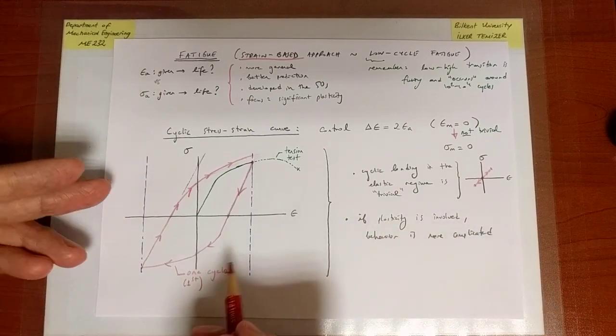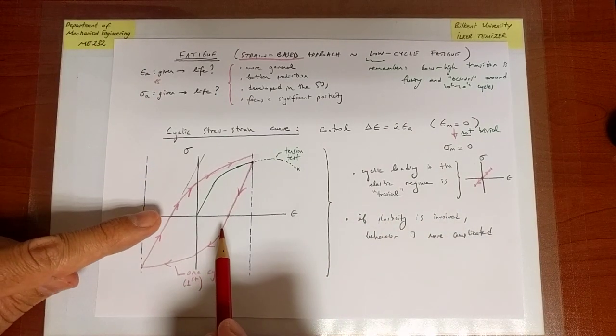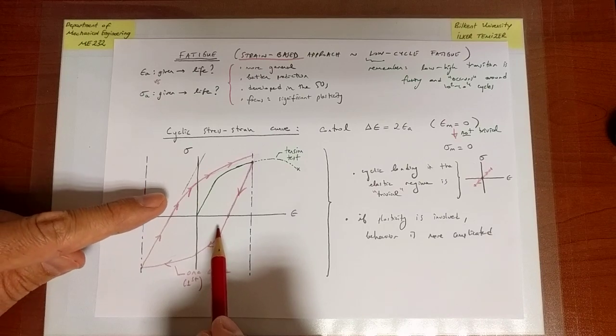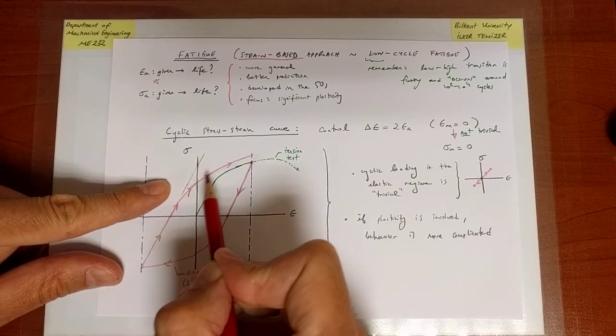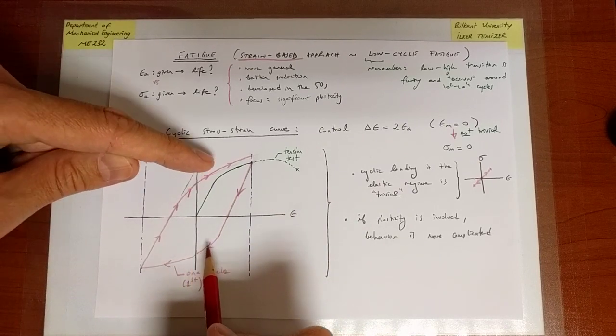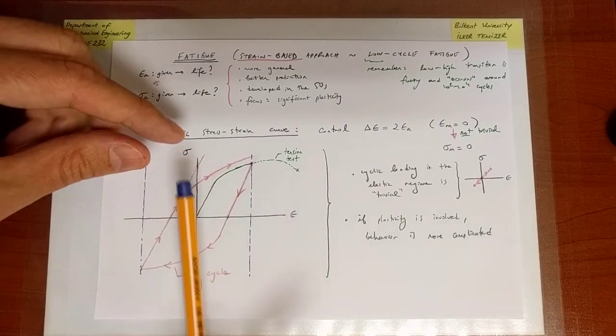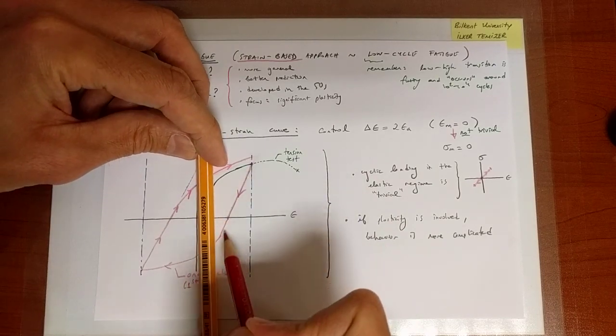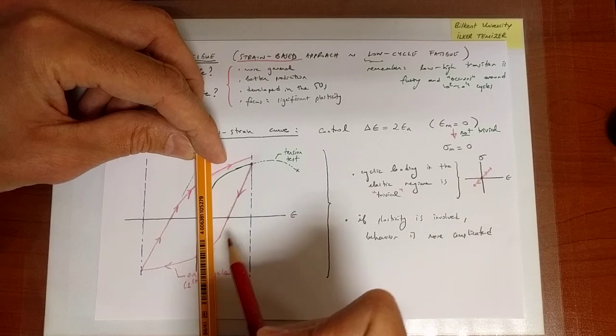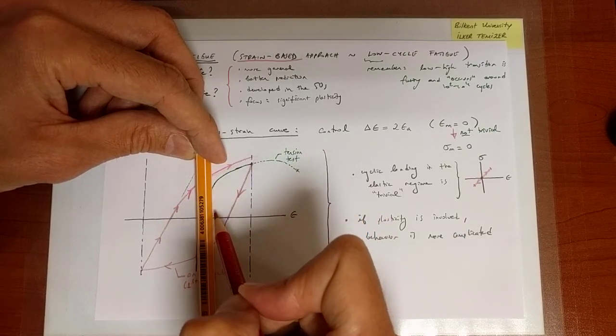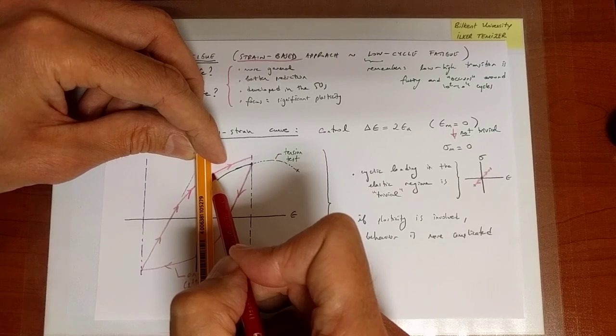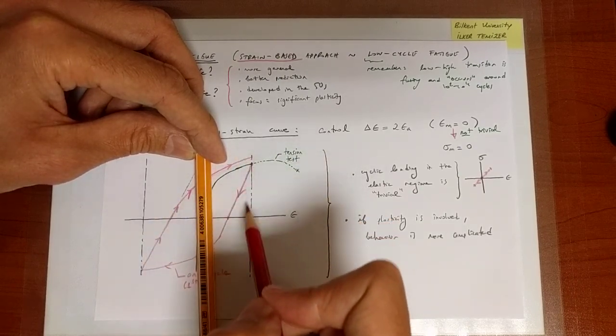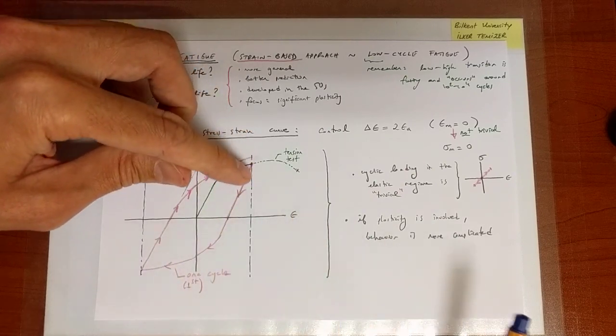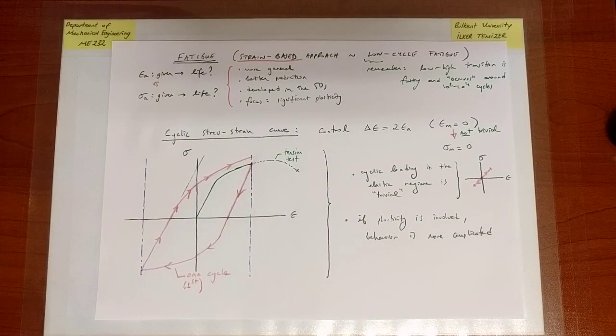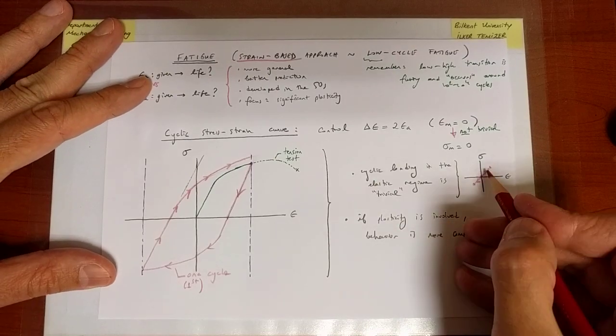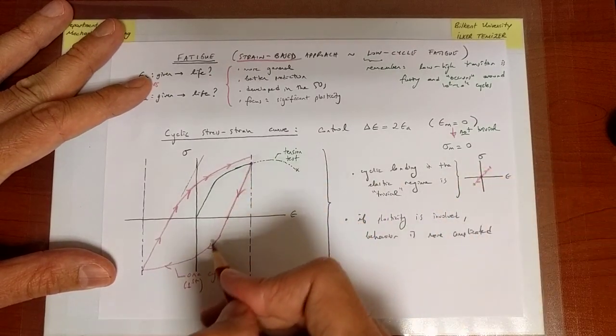If plasticity is involved, the behavior is a lot more complicated. Now, what we also see in such cases is that when I go in one direction and follow back in the other direction, there's a significant gap at any given strain. Let's say at that value of strain, the stress along one direction is compressive, and the stress along the other direction of loading, at the same value of strain, is significantly positive. So the difference is just between the loading directions. Okay, so we call such a loop one that displays hysteresis. In this case, there is no hysteresis. We load back and forth along a line, but here we have a hysteresis.